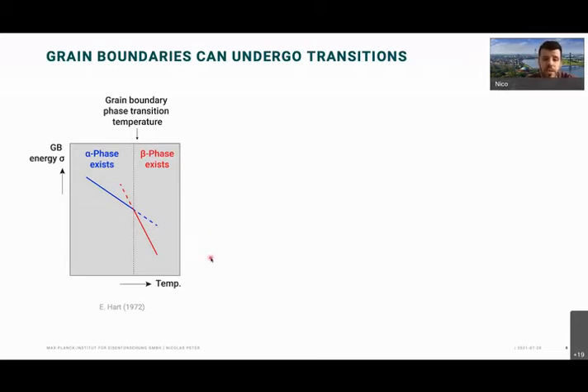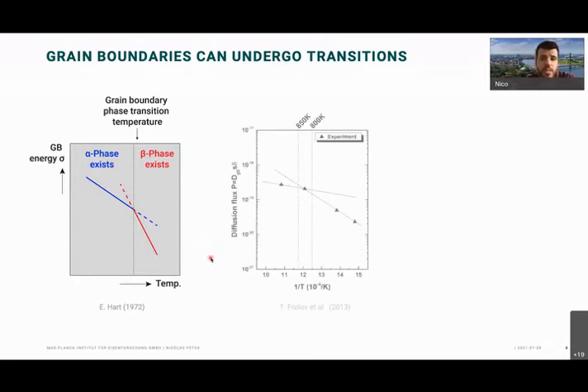Not facets in a sense that you form a grain boundary facet, but it can have very different appearances. So this concept was then experimentally kind of shown in a paper in 2013 by Tim Frolov, who showed that the diffusivity of a grain boundary changes with increasing temperature. And this diffusivity is actually of silver atoms in a copper matrix or in a copper grain boundary. So increasing the temperature, eventually this slope changes. And as this is an Arrhenius plot, the slope shouldn't change. So this change is unexpected and was attributed to a change of a grain boundary phase, so a transition. And then he performed some simulation experiments and could reproduce this.